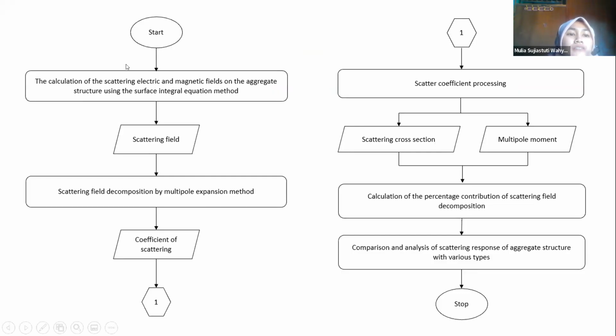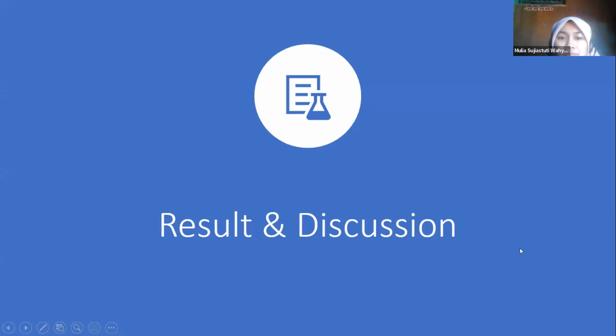Okay, we start with the calculation of the scattering electric field and magnetic field on the aggregate structure using the surface integral equation method. We can find the scattering field. The scattering field we decompose by the multipole expansion method. Again, we can find the scattering coefficients. With the scattering coefficients we can find the scattering cross-section and multipole moments. And then we can calculate the percentage contribution of the scattering field decomposition. And then we can compare and analyze the scattering response of the aggregate structure with various types. Okay, there is the result and discussion.